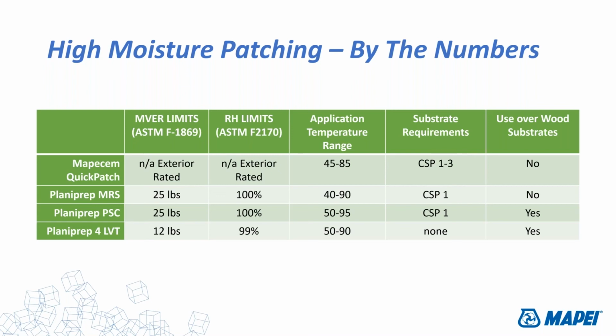We like some porosity, temperature range 40 to 90. Can't use it over wood because it just doesn't have any polymer. It's very brittle, designed for use specifically over concrete. PSC, on the other hand, enhanced characteristics, 25 pounds, 100%. 50 to 95 is the temperature range. Yes, we'd like to have some porosity when you're installing it on a concrete slab. And yes, you can also use this product over wood substrates, approved wood underlayments like exterior grade plywood, if you could afford to buy it these days.